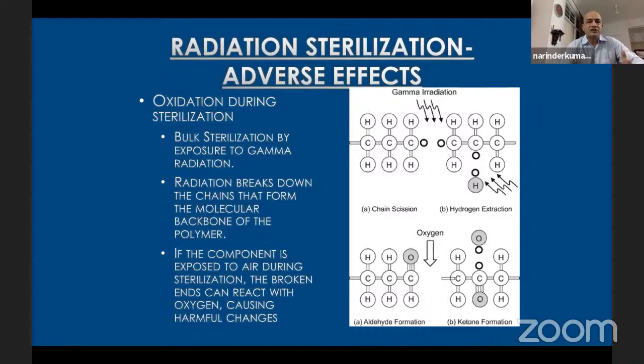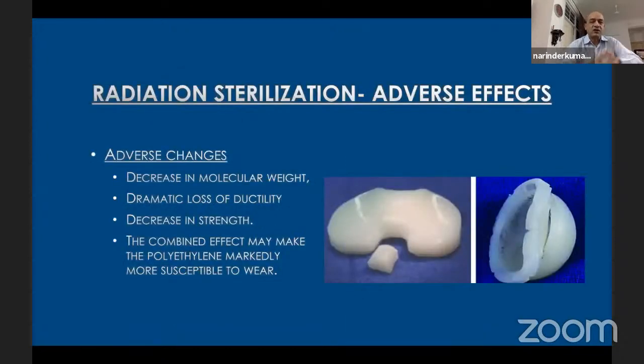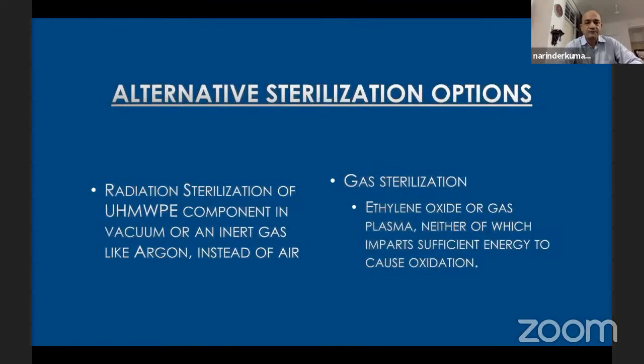The sterilization, number one, if we do what the industry says, bulk sterilization by radiation, that leads to oxidation of the poly. That oxidation reduces the mechanical properties of the poly, in the form of decrease in molecular weight, loss of ductility, decrease in strength, and we have disastrous breakages of poly, both in the knees and in the hips.